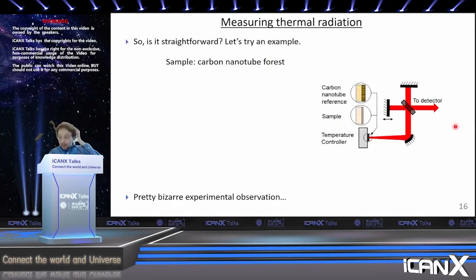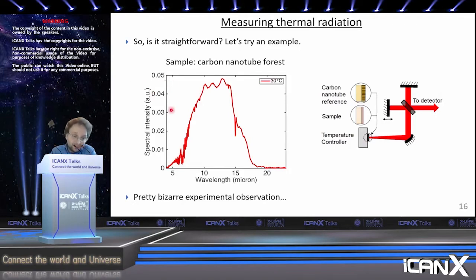So I want to show you an example of some of these experimental difficulties. This was a very amusing problem that we found in our lab that took us a long time to overcome. Our sample is one of these carbon nanotube forests, so it's essentially a laboratory black body. And all we're doing here is putting that on a temperature controller and sending the output into a Fourier transform spectrometer and just measuring a spectrum of thermally emitted light. So here is a measured spectrum.